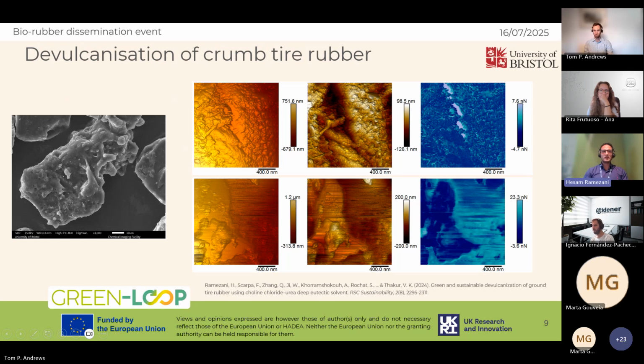To confirm the results, we used SEM and AFM microscopy. As you can see in the left-hand side SEM image, the surface of the rubber is plasticized and looks molten, which shows that the devulcanization has actually affected the rubber crumb. And on the right-hand side, on top, we have the AFM images of untreated rubber. As you can see, the surface is very rough, while the below image, which is after devulcanization, shows a smooth surface. And actually, the average adhesive force was 5 times greater than that of the untreated rubber, which shows that the surface of the rubber was very sticky after devulcanization. Next, please.